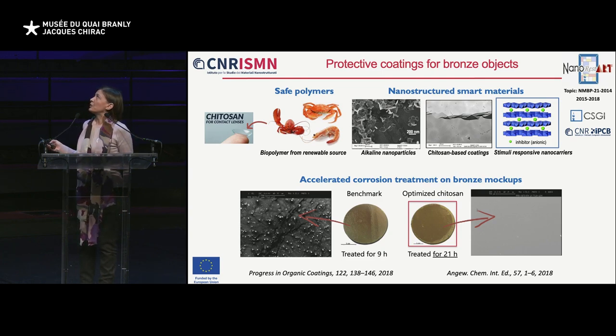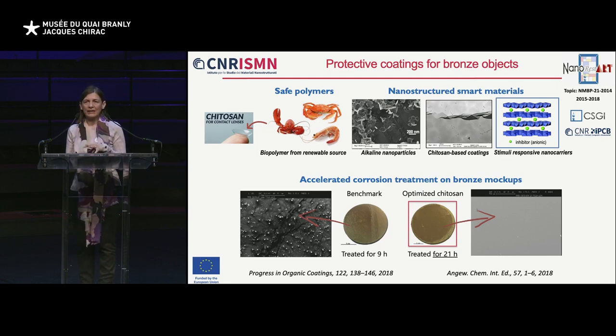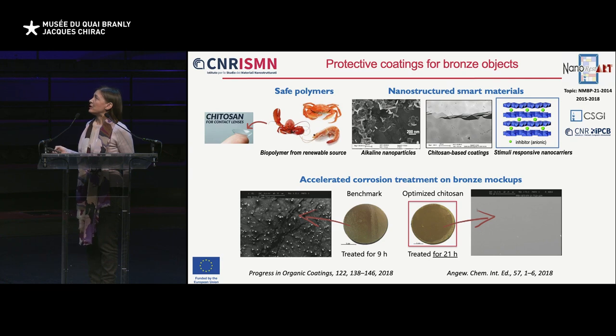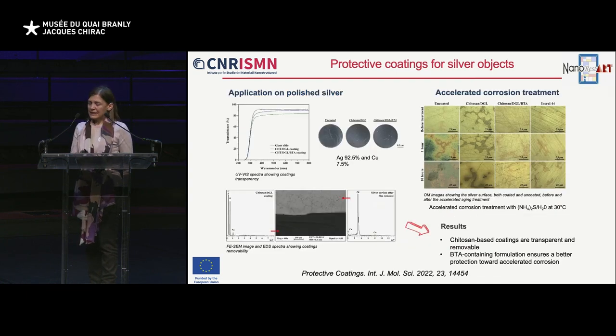So once optimized the formulation, we functionalize the biopolymer coating with nanostructured smart materials, also with the nanocarriers able to release the protective molecules, which in this case is a corrosion inhibitor, only in the presence of degrading species. So the idea is, like in the drug delivery, we can locally release the protective molecules only when and where necessary. So I will just summarize one of the main results of the previous project, because in this case, by using optimized chitosan coatings applied on bronze mock-ups and by performing accelerated corrosion treatment in the presence of acidic water vapors, we can see that we can improve the protective efficacy compared to the commercial products that we selected as benchmark.